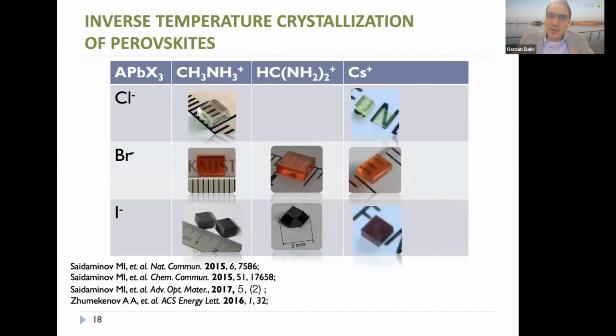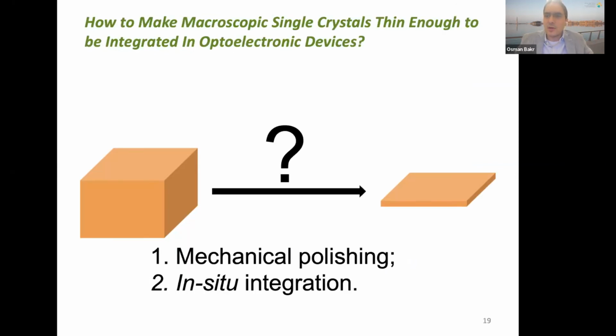So we showed that this inverse temperature crystallization method is actually quite general and occurs in most metal halide perovskites, and can be used to generate single crystals of many compounds. So how can we apply single crystals for devices? Bulk single crystals are difficult to integrate in devices because in devices you need very thin crystals. So you either find a way of polishing the crystal and cutting it, or you find a way of growing the crystals thin.